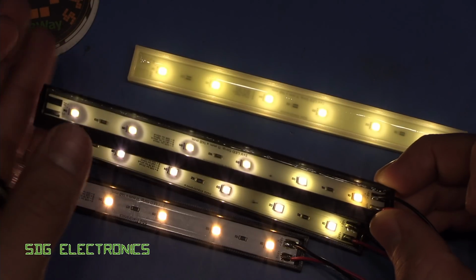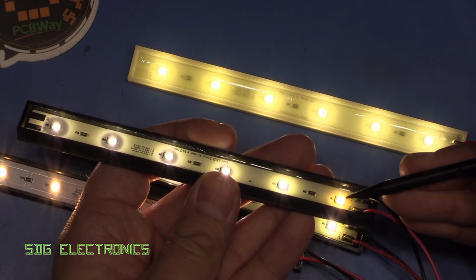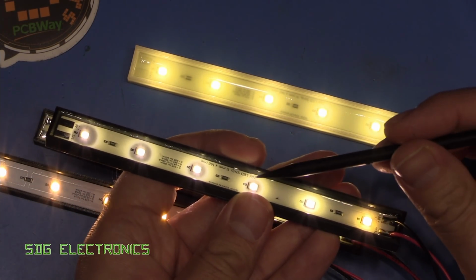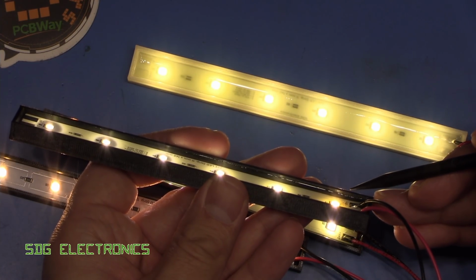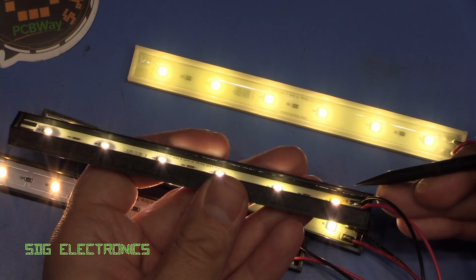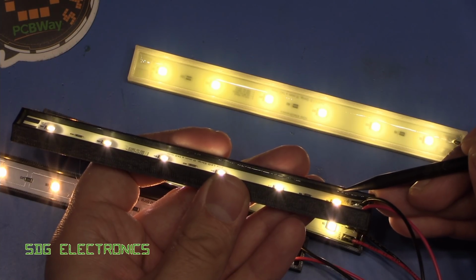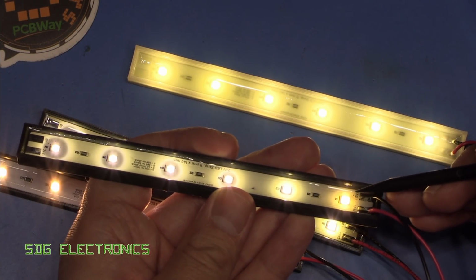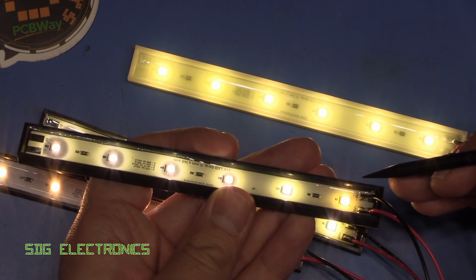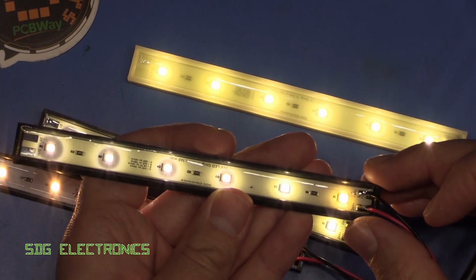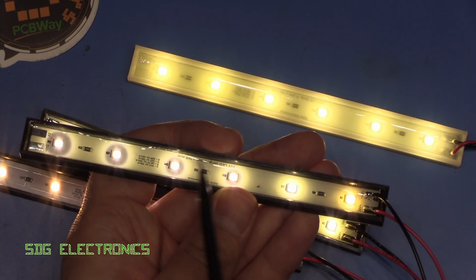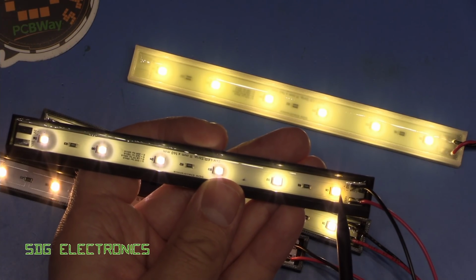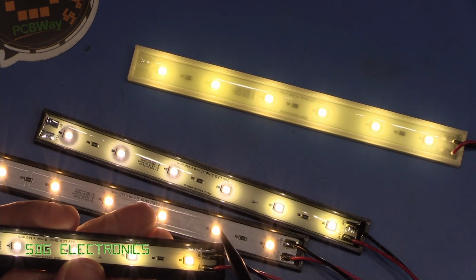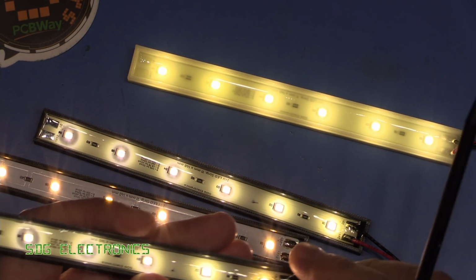Now, interestingly, if you take a look, this one is quite a lot warmer white than these ones. And I did actually end up somehow pouring the resin a little bit thinner in this area. You can see it going down just in this area here. So it would appear that the depth of resin shifts the colour temperature. So yeah, it's quite weird. We've got quite a cool white here going towards this warmer white, but not quite as warm as these ones with no resin whatsoever.